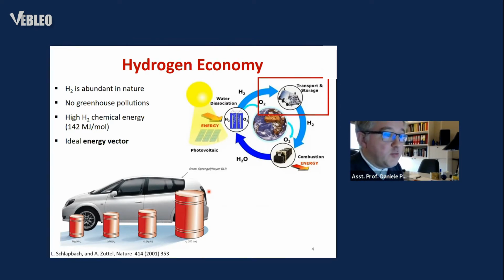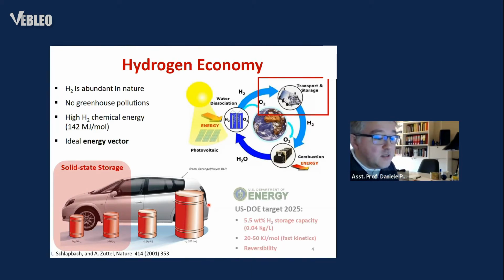this gas. The most common strategies adopted so far are represented by physical storage, namely compression and liquefaction at very low temperature, but both of them are faced with severe technological problems and still too low storage efficiency. The scientific community agreed that the best way to store hydrogen is solid-state absorption. Basically, hydrogen is physically or chemically bound in a compound with the right energy and in a reversible way. So far, many compounds have been isolated with good hydrogen storage properties, but none of them still meet all the strict requirements of the US Department of Energy, and they are far from competing with the performance of a common gasoline tank.